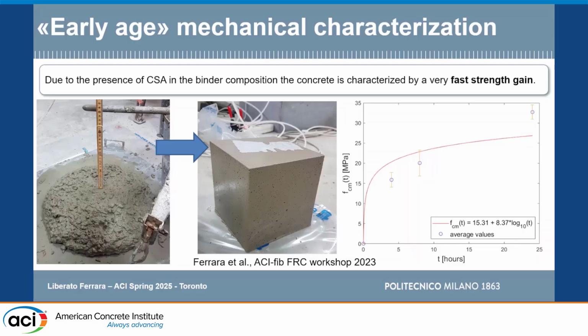And these are the results of the very early age, we started measuring at 4 hours. At 4 hours it is already hardened. You can use regular testing protocols and so on. As you can see, at 4 hours, we already have about 15, 20 megapascal compressive strength.